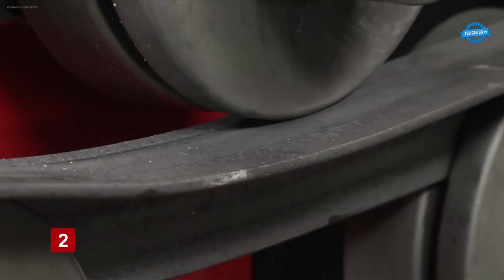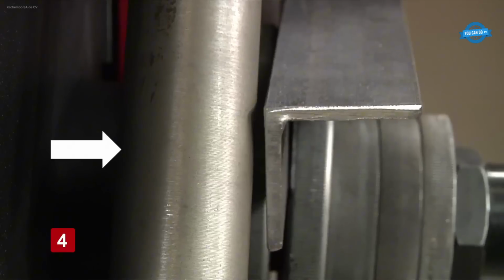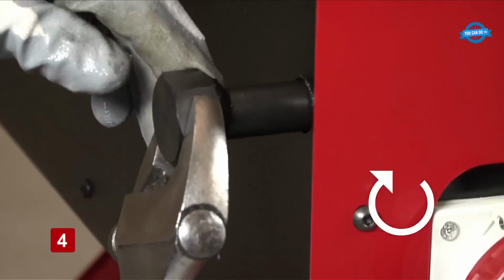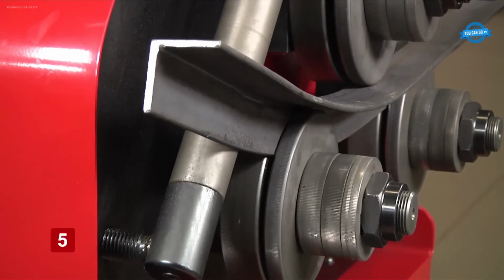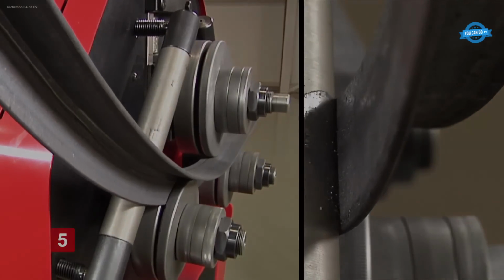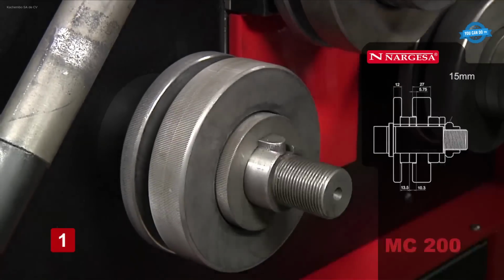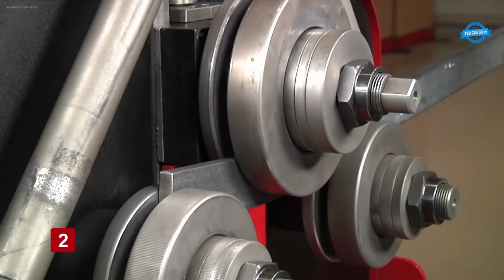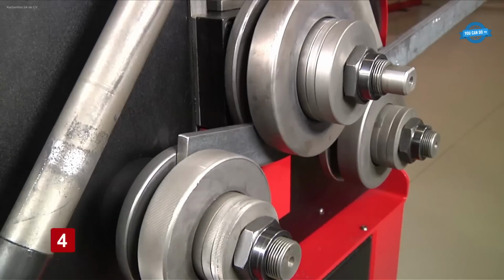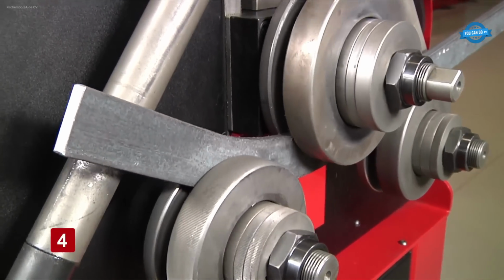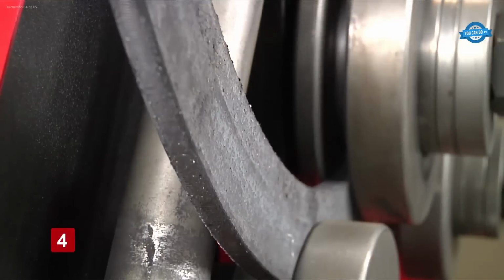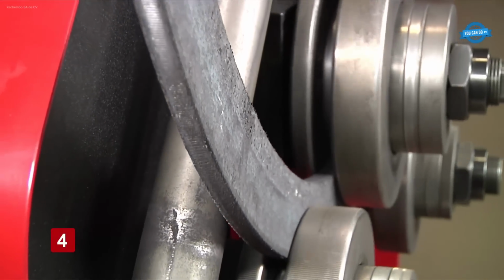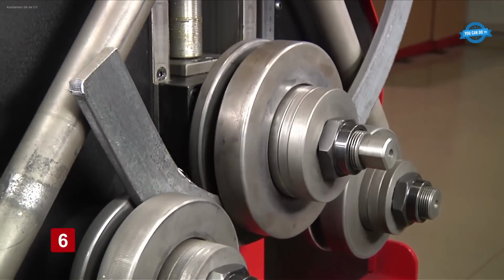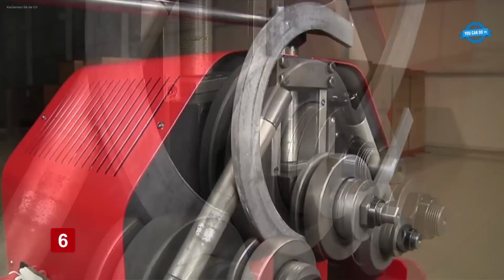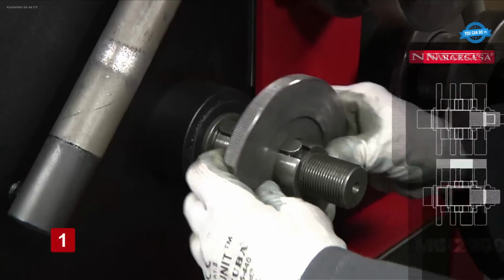The MC200 features two knurled, motor-driven lower rollers for maximum traction, along with hardened and ground steel shafts measuring 40 mm in diameter and 74 mm in usable length. The distance between the lower shafts is 286 mm, and the machine can bend round tubes up to 2.5 inches, 63.5 mm. Bending is adjusted through the upper shaft, allowing precise control without deforming large diameter profiles.